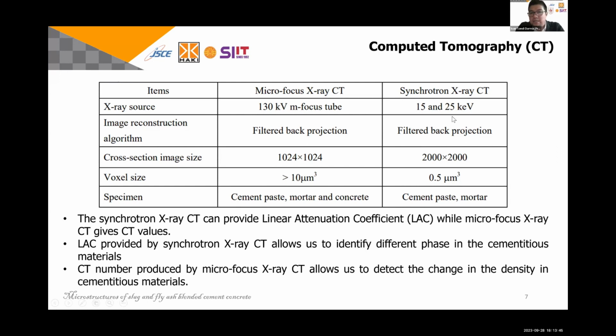Synchrotron X-ray CT is usually used for the cement paste phase. But for microfocus X-ray CT, the sample size can be quite large compared to synchrotron X-ray CT. In our recent research, we could achieve around 15 to 20 micrometers, and the specimen could be cement paste, mortar, and maybe concrete.